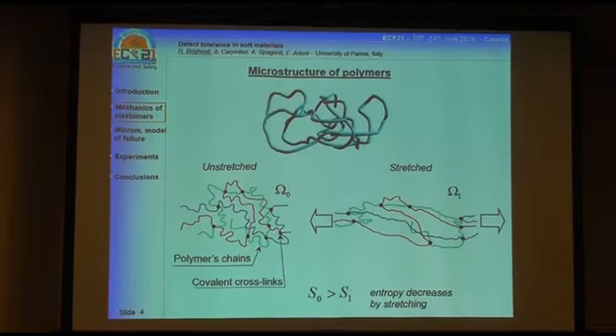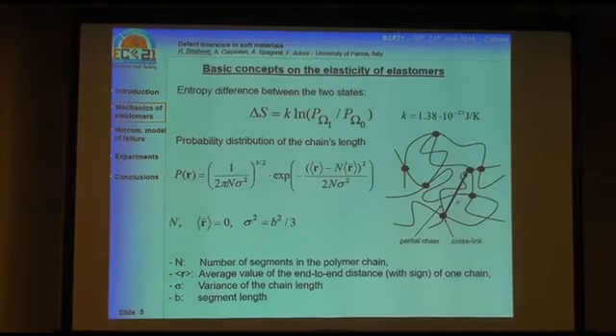So this is a scheme of what we can observe by considering a polymer. We have a very long molecular chain. Normally we have many entangled chains which are linked together at several points that we call crosslinks. And if we observe what happens to the material when we stretch it, all these chains become more aligned along a single direction, and they are stretched, so the elastic energy is mainly contained inside the single chains that change completely their initial conformation. So we have a decrease of the entropy because of this geometrical phenomenon.